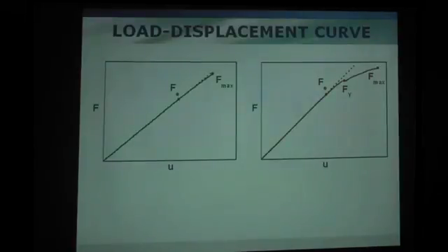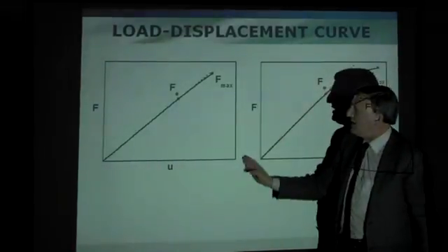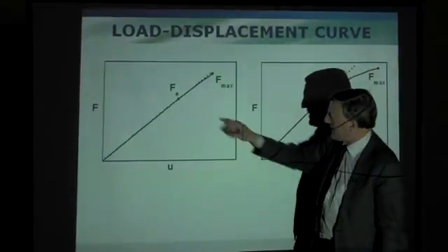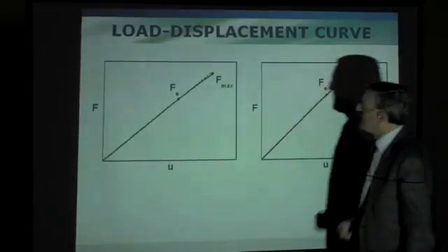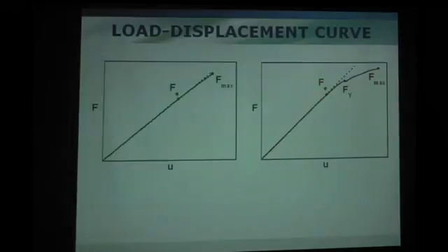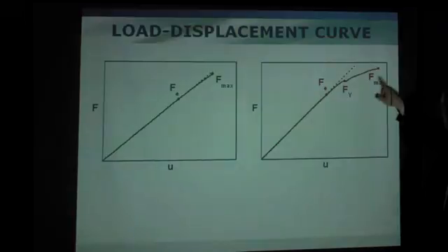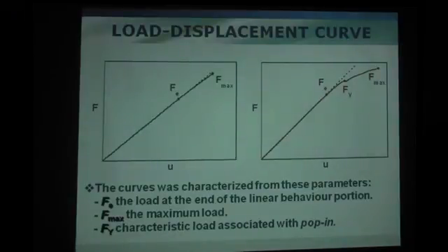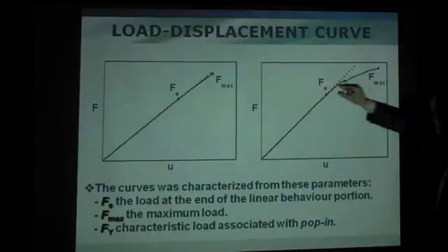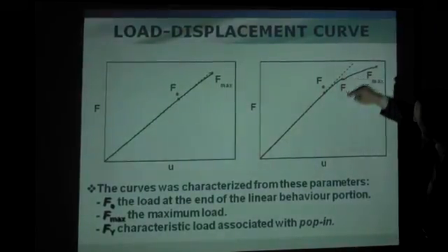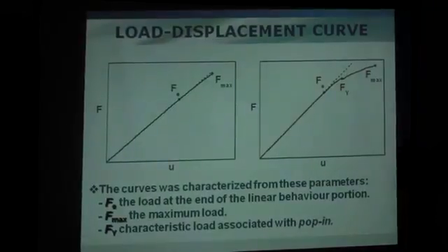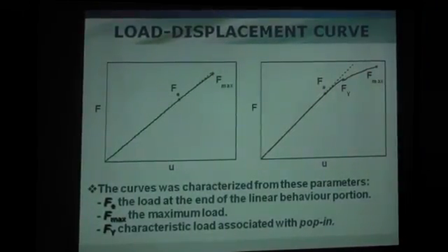And here the load-displacement curve for 0 to 4 steps of cold drawing, slightly drawn steels or hot rolled material, not drawn at all: mode 1 behavior was a linear plot, and we have a non-linear plot for heavily drawn steel, but it is not caused by plasticity. To a certain degree, yes, but it is very confined, a low level of plasticity. We define Fy and Fmax, and Fy is linked with the pop-in phenomenon, a pop-in produced by a burst, by sudden tearing, by anisotropic tearing. This is when the embryo of crack deflection appears here in B7, and we obtain the pop-in, but we still have load-bearing capacity of the wire.